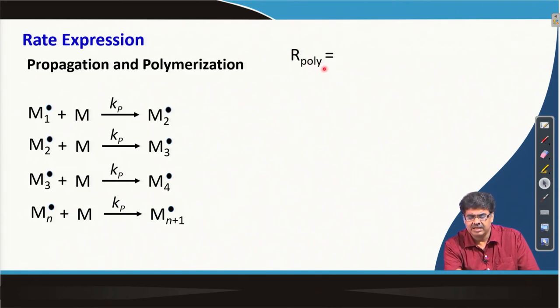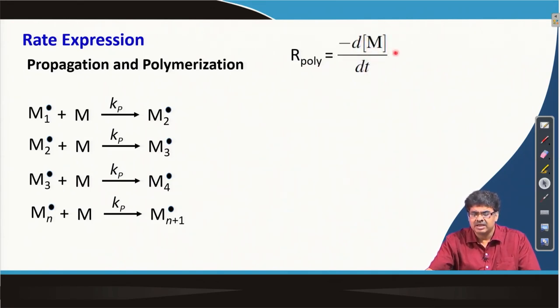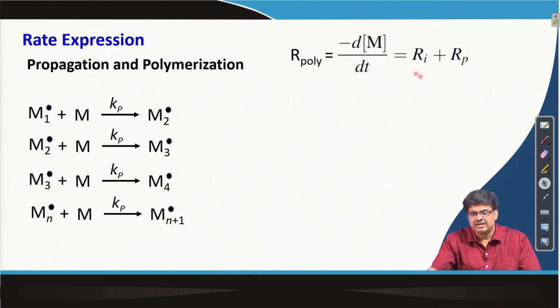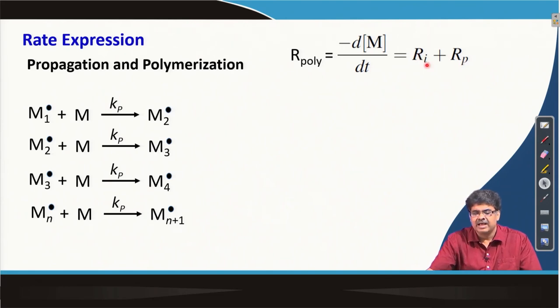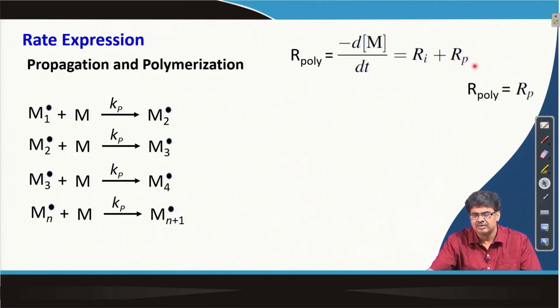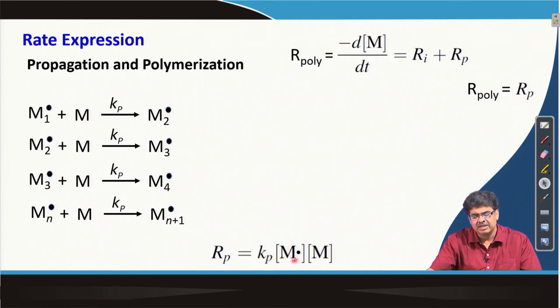The rate of polymerization is given by the rate of disappearance of monomer. Monomer disappears in the initiation step and during all propagation steps. So the rate of polymerization equals rate of initiation plus rate of propagation. Since only one monomer disappears in the initiation step while there are many propagation steps, we can consider the rate of polymerization approximately equal to rate of propagation: R_p = kp [M dot total][M].